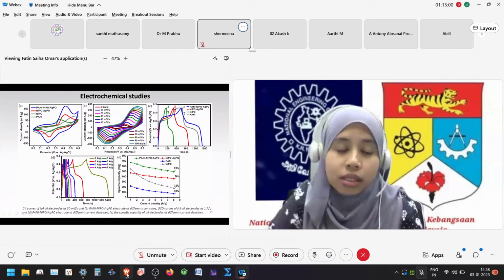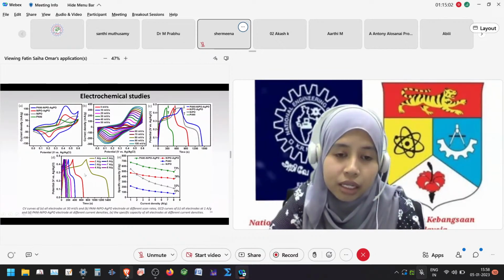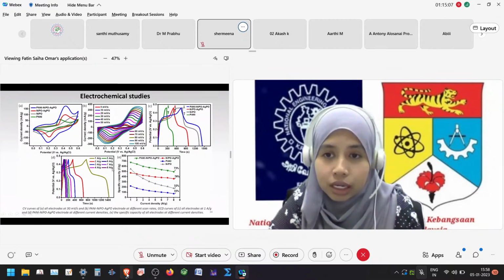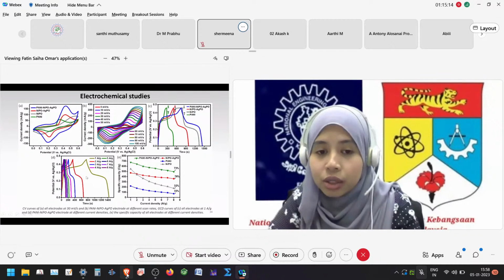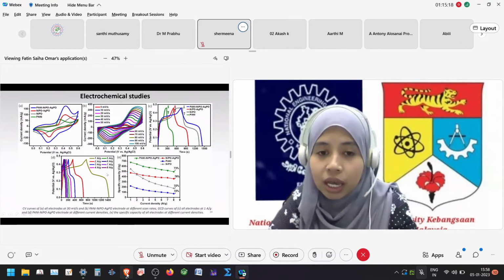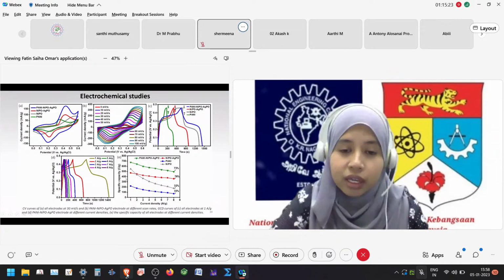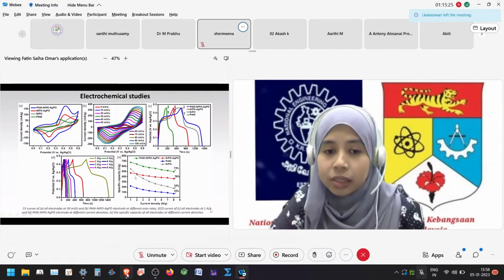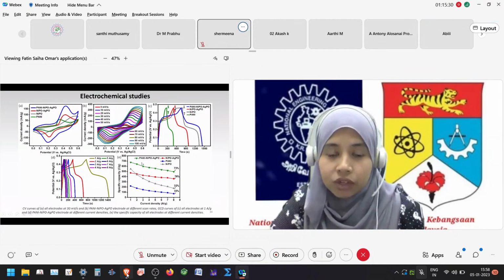And figure D is the GCD, where we varied the current density from 1 to 8 ampere per gram for all electrodes. So this is only the curve for one electrode, and we have to run the other 3 electrodes. So from the GCD curve, we can calculate the specific capacity and plot this graph. From here, we can see clearly which sample has the highest specific capacity. So in this figure, polyaniline nickel phosphate silver phosphate has the highest specific capacity.